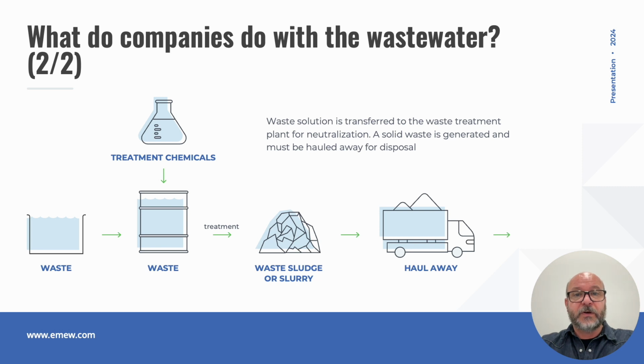In the second scenario, these wastewaters can be treated on-site. In this case, the pickling or etching solution would be transferred to the on-site waste treatment facility. The wastewater is then treated to neutralize the acid and to precipitate the metals by adding a form of alkali, typically caustic soda or lime.